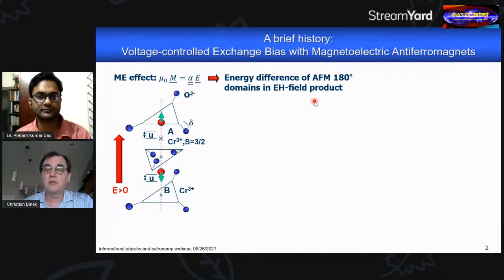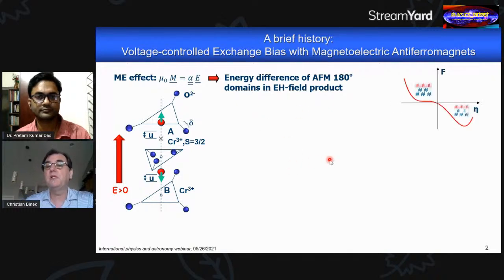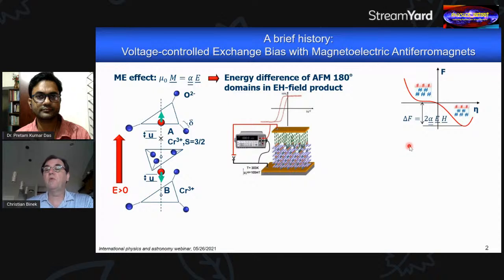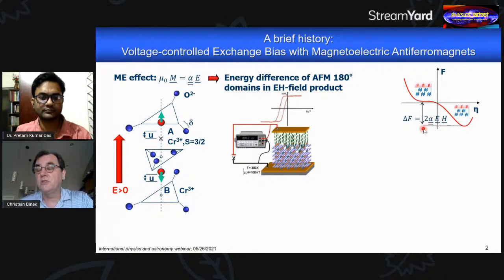And if you crank up the electric field, for example, then you can determine whether a particular domain is in one state or the other state, depending on the sign of the electric field you apply. And that is depicted here. So you see basically the free energy landscape with 2 minima which are same energetic levels in the degenerate state. And then if you apply a product of electric and magnetic field, you can lift this degeneracy and make one domain state energetically favorable over the other.